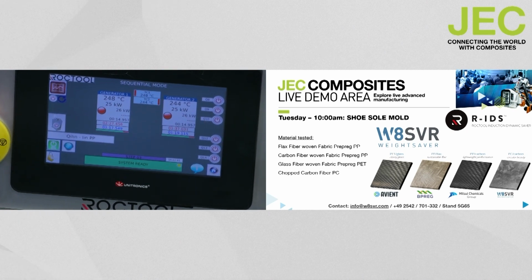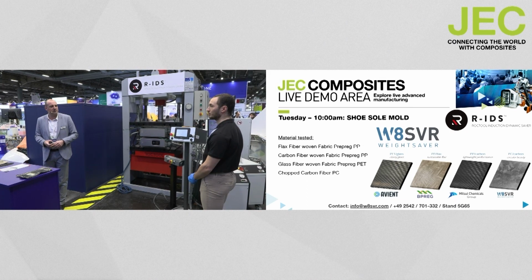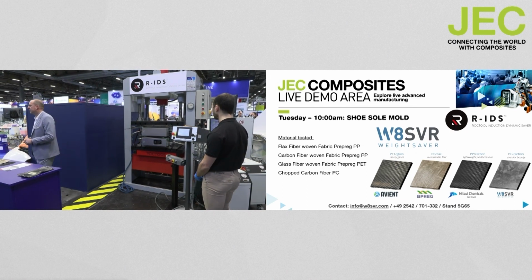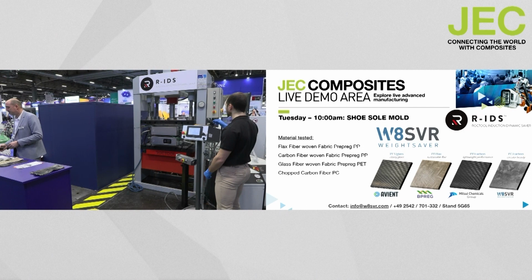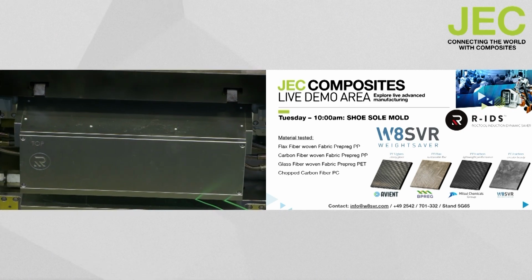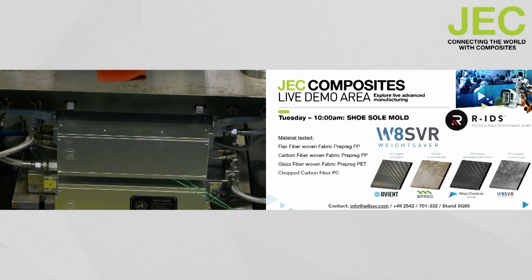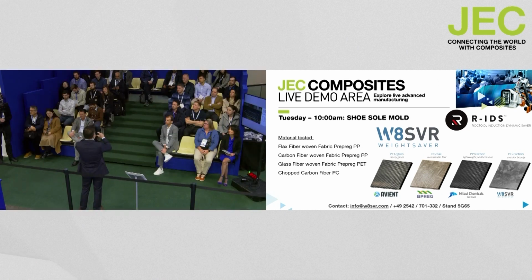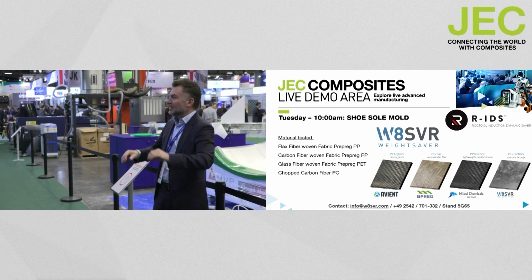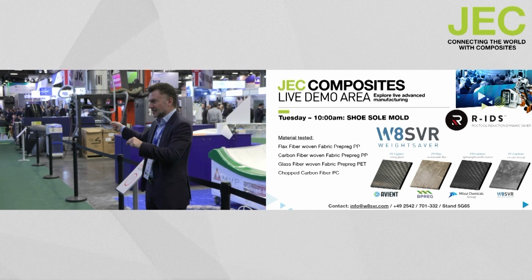And how long is the cooling stage for this one before demolding? 90 seconds. Okay, it's very short. Because the insert is cooled down and separated from the heated element, you can really reduce your cooling time in general without being interfered with by the platen itself, because the insert is cooled down on its own. But the platen also has a cooling network to cool down to that step temperature, ready for the next cycle.